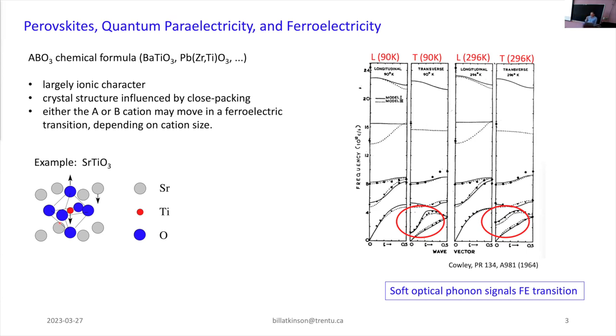And specifically, I'm interested in transition metal perovskites. It's a huge family of materials. And so the thing about perovskites, at least the transition metal ones, is that they've got largely ionic character. And so this means that the crystal structure is really heavily influenced by close-packing considerations. So the way that picture is drawn, there's a lot of space between the strontium and the oxygen and the titanium and the oxygen. But in real life, everything is touching everything else. And you're trying to maximize your packing, minimize the amount of space in there. And that's because the strontium is nominally 2+ and the oxygen is 2-, and they want to get close together. Similarly, the titanium is 4+ and the oxygen is 2-. Now, the titanium is slightly too small for the space that's available to it.